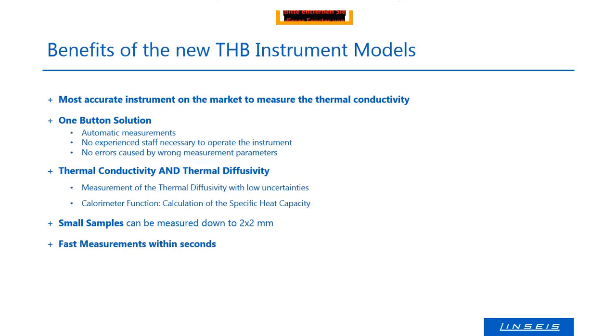Then the measurement you have seen is quite fast. It's within seconds, below 1 minute. And there is a special sensor. I didn't show it today, but we have it. It's a single sample sensor, which you put on the sample. You need only a surface, and you can put the sensor on any sample and measure. You need not cut out something and prepare the sample. Just put the sensor on and measure. It's not as accurate as the double sample method, but it's within 10%.